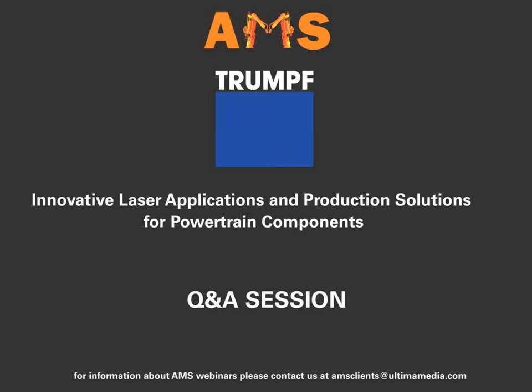Compared with the EB welding process, I would say the biggest advantage is we don't need this really deep pressure or vacuum, in the case of EB welding. We just need a pressure between 10 or 20 millibars, something like this, and we can reach a very, very good welding result. And we can use our laser network. That means we can have 1 or 2 or 3 exits per laser, and we can have 2 of these little chambers. While we are welding in the first one, we can evacuate the second one and the third one. So the evacuation time is nearly 0 in such a concept.